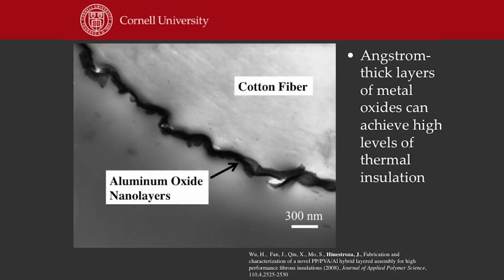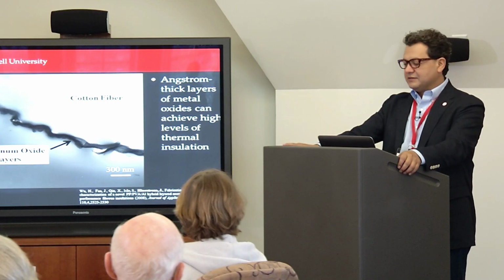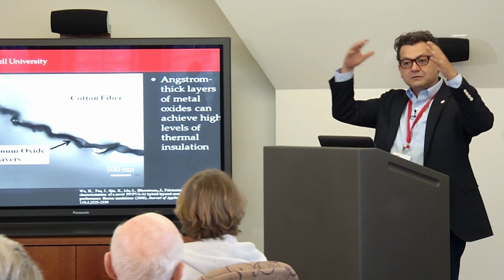So you can have, in Ithaca, you guys remember when you were here, we have winters of -40, -30 degrees. You may not want to remember, but that's our case. But now you have enhanced insulation by using these very small layers. So maybe you don't need this 2-inch thick coat when you can have a T-shirt with 50 angstroms of coating. Yeah. So now this is a completely new way of thinking.